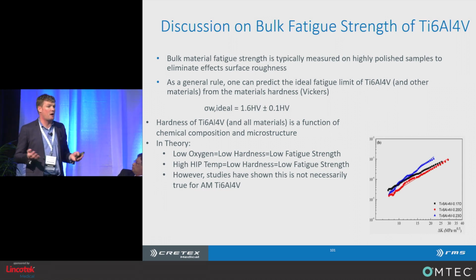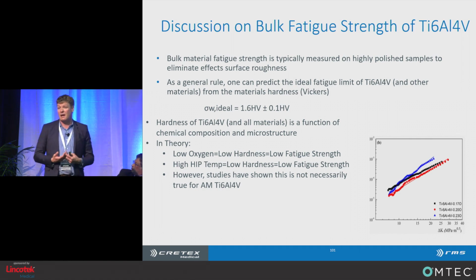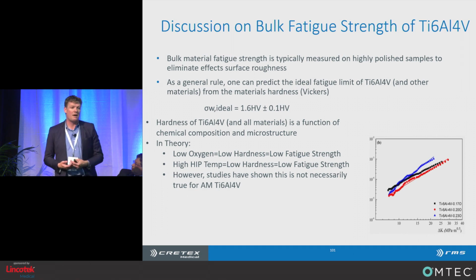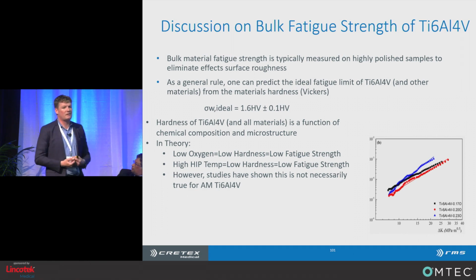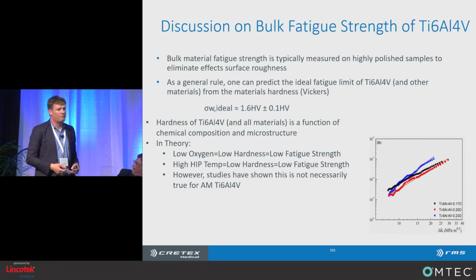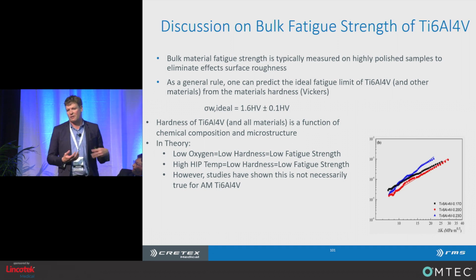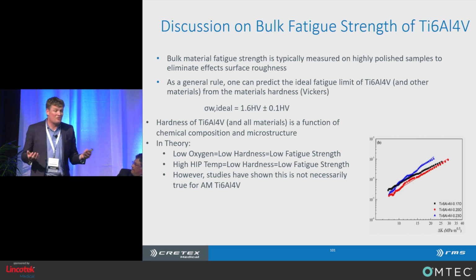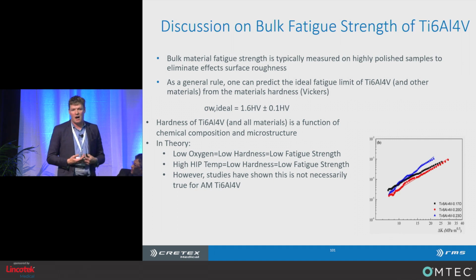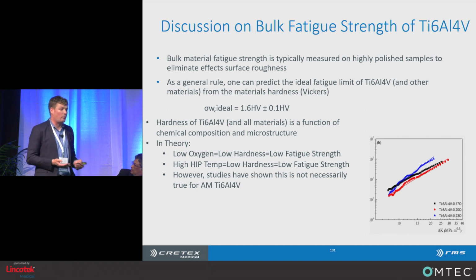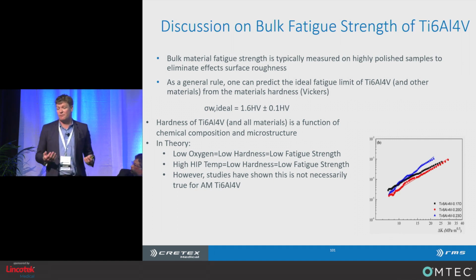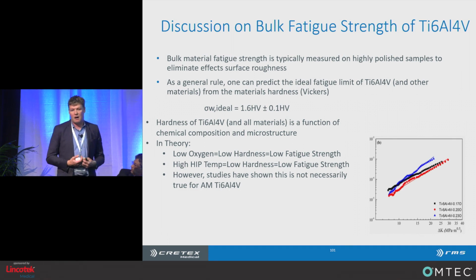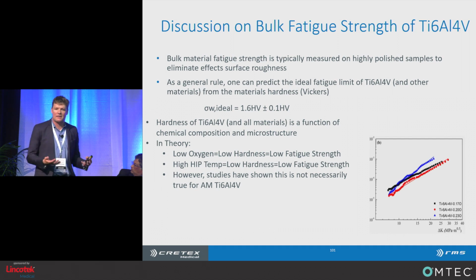A lot of you are probably familiar with wrought Ti-6.4 and its fatigue performance, and typically there are two grades of Ti-6.4. There's grade 23, extra low interstitial Ti-6.4, and then grade 5, which allows for additional interstitial elements in the material. In general, grade 23 was developed as an alloy that had better fatigue performance than grade 5 because of those lower interstitial elements, right? And those were typically wrought and cast materials.